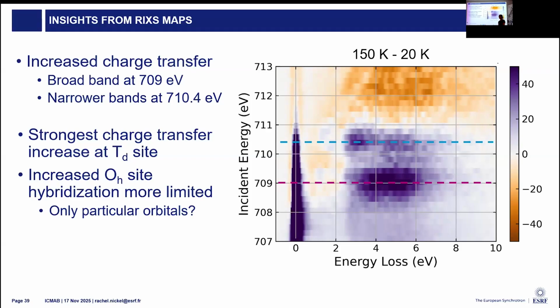Yes. So these are all very processed data. This is a powder sample, so even the amount of sample that's in the beam will change as a function of temperature. So we normalize these to the DD excitation. There's one DD excitation that we associate with the regular octahedral site, and everything is normalized to that one point. We chose this because when we look at a film sample, which is much more homogeneous compared to the powder, we know that that DD doesn't change as a function of temperature. And so that's our normalization of intensity for both of the maps.